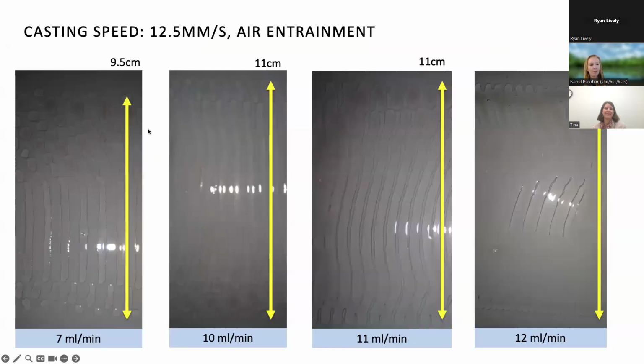And so this is how we proceed. Now, when we have a new dope, when we have our dope with our green solvent, we have no historical data on how this is going to operate. So we have to develop a casting window by ourselves. And if we start out with trial and error, we can get to where we have dripping. So these are dope lines that are just not making a membrane, or we can get it to where it is a membrane, but it develops scratch lines, again, because our flow rate and our velocity are not matching correctly, and so they're not making a viable membrane.